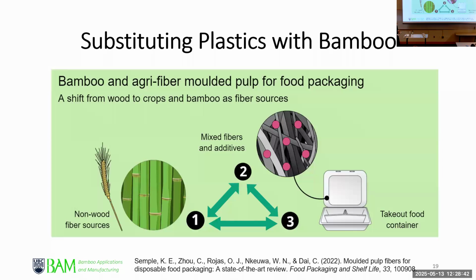So the idea is simple. When it comes to takeout food packaging, you use it for like 30 minutes and you throw it away. So really you try to find the cheapest or most renewable fiber possible. So the template there is, instead of using wood, you use an annual waste fiber like grass or straw. And then there's inherent deficiency in these fibers compared to bamboo, so bamboo becomes an enhancer for these materials. And then of course you add some additive for performance.